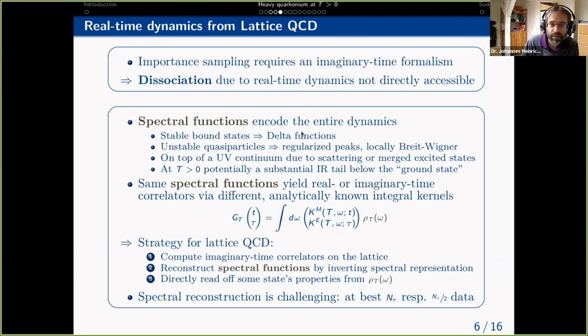So if you have bound states, they are represented by delta functions in the spectral function. If you have unstable quasi-particles, like decaying or dissociating quarkonia, that would be some sort of regularized peaks that locally look like Breit-Wigner, but certainly are regularized because the integral of the spectral function has still to remain finite. And all of these peaks would be sitting on top of some UV continuum, which is either due to scattering states or due to some sort of merged excited state contribution where the peak structures are overlapping. And at finite temperature, we get on top of this a substantial IR tail contribution that is sitting at lower frequencies than the actual ground state that we want to consider.